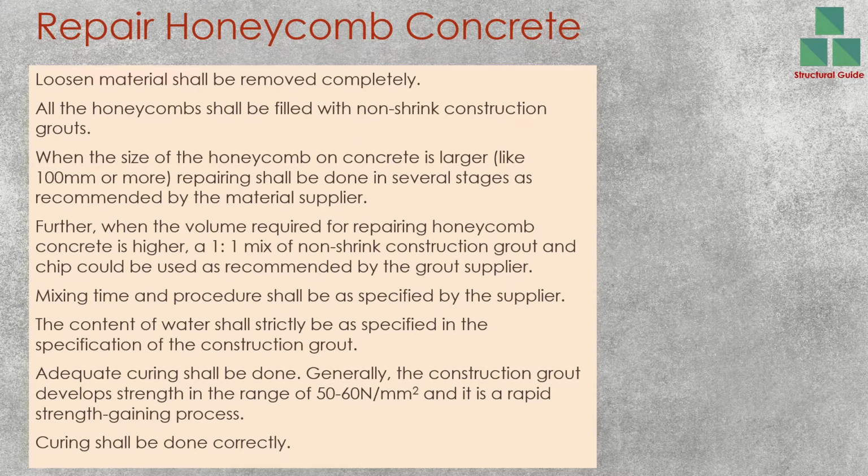When the size of the honeycomb is larger than 100 millimeters, repairing shall be done in several stages. This may also depend on the supplier's specification. Generally, if the depth or the height is greater than 100 millimeters, you might do it in two pours.